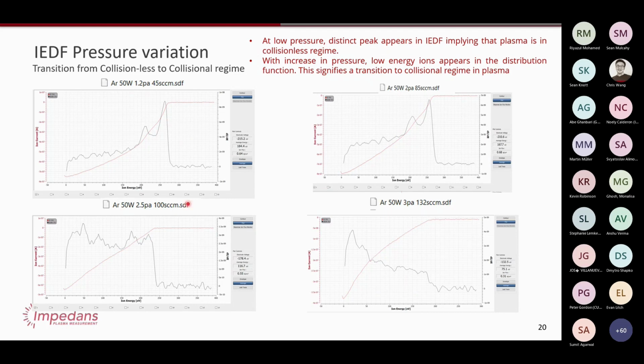So yeah, maybe while these graphs are up, I'll just talk a little bit more about the measurements here. Over here, it's maybe a bit hard to see, but this is the average electrode voltage. So in other words, when you apply RF to an electrode, as I showed earlier, you have this RF on the bottom, you have the plasma potential, but the RF is kind of pushed down by the plasma potential. What I mean by that is, you end up with what's called a DC self-bias on the electrode that you apply RF to, and that's usually some large negative voltage.